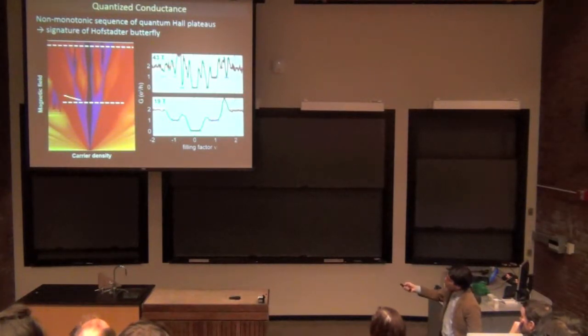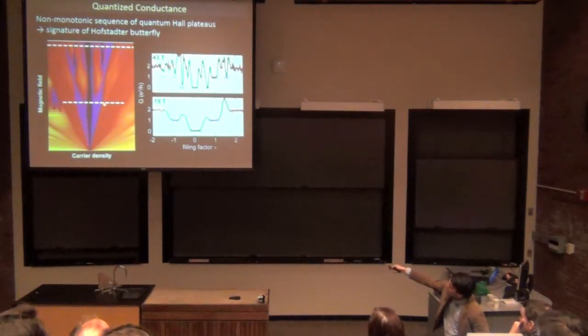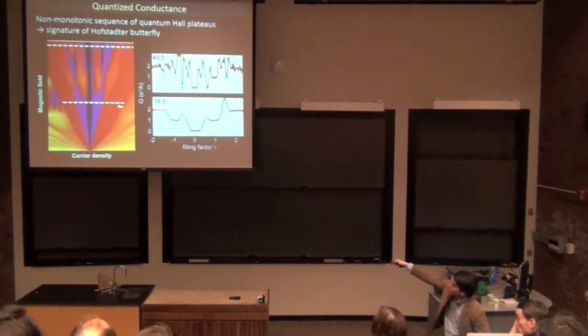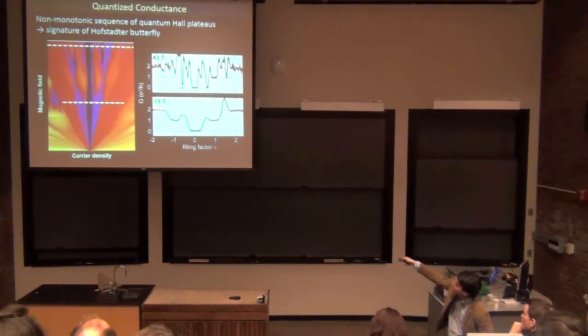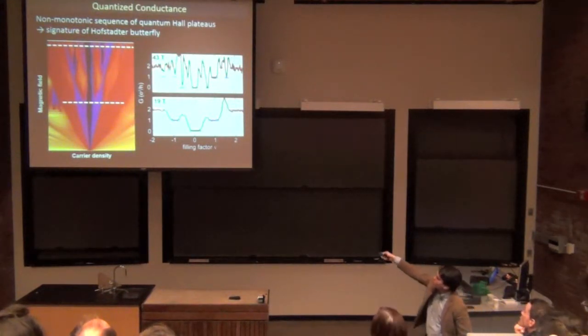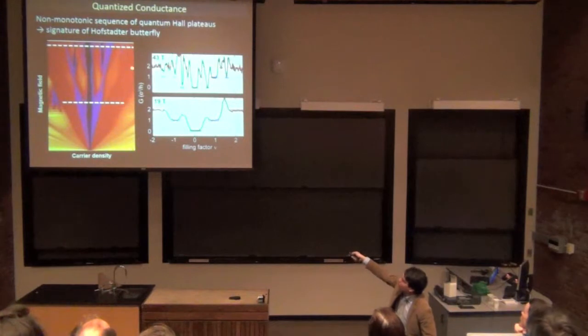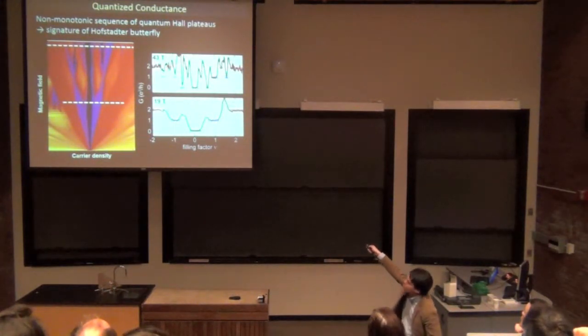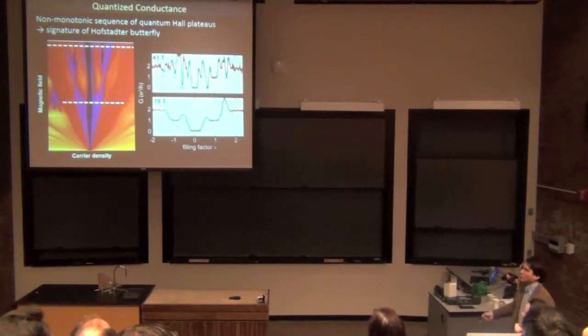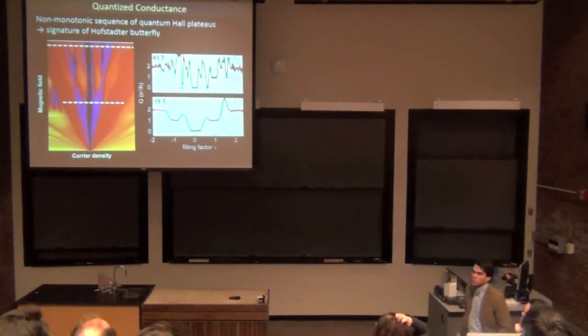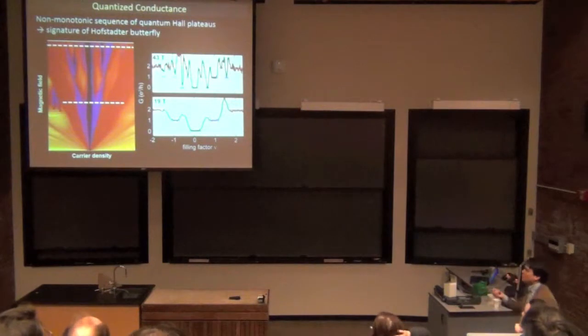If you look at low magnetic field, 19 Tesla, and just concentrate on the colors, you can see this sequence 0, 1, 2, a very simple monotonic sequence of quantum Hall plateaus. But if you go to the high field regime, where phi over phi naught is greater than 1, you can see this 0, 1, 0, 1, 2, 1, 2 sequence of quantum Hall plateaus. So that's really the signature of this Hofstadter butterfly that we're seeing in transport.